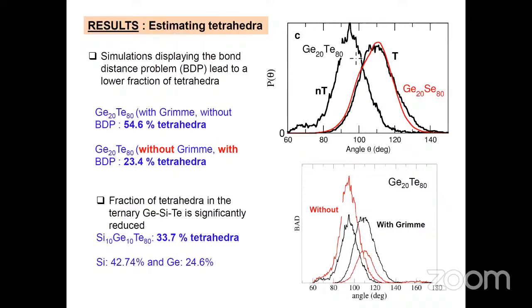Furthermore, I should mention that with the Grimme correction, you get a fraction of tetrahedra which is much larger than in a simulation without the Grimme correction. In fact, without the Grimme correction, you will find only about 23% of tetrahedra. And this is linked with the bond distance problem, because the smaller the distance, the larger the fraction of tetrahedra you will find. This is a feature that is very well known in the polymorphism of silica, for example, where the bond length increases with the fraction of the octahedral population. So we can play the same kind of games with ternaries for various systems, extracting the fraction of tetrahedra. Here again, I plot for the same system the bond angle distribution for both populations with the Grimme correction or without, where obviously without, you see that the contribution from octahedral or defect octahedral germanium is enhanced.